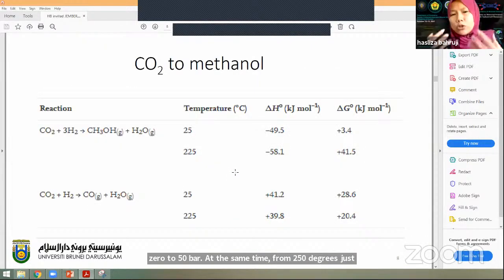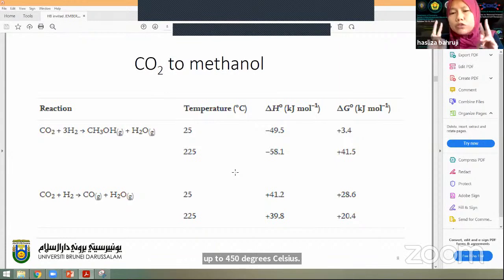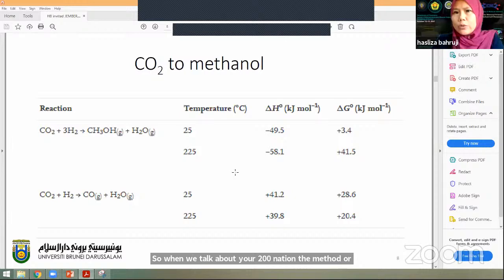When we talk about CO2 hydrogenation to methanol, there are always 2 competing reactions. The first is CO2 hydrogenation to methanol, which has a negative delta H and also a positive delta G, so this reaction is not spontaneous, and it favors low temperature but high pressure. But the competing reaction that we always have to deal with is the reverse water gas shift reaction, which is a reaction of CO2 with hydrogen, but instead we get carbon monoxide.